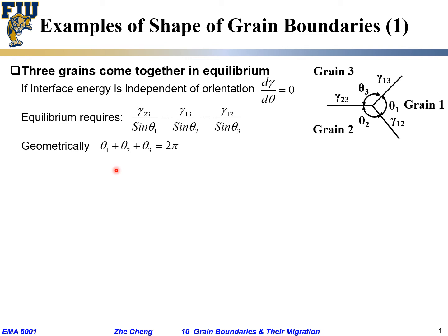Don't forget that all three angles add up to 360 degrees or 2π. If we are dealing with a completely homogeneous single-phase material with high-angle grain boundaries, all three γ values should be the same. High-angle grain boundaries are no longer sensitive to orientation — that value is roughly one-third of your surface energy. When all three gammas are equal, all three theta angles are equal, and since they add up to 360°, each angle would be 120 degrees.